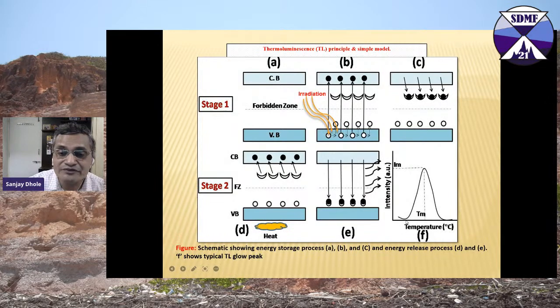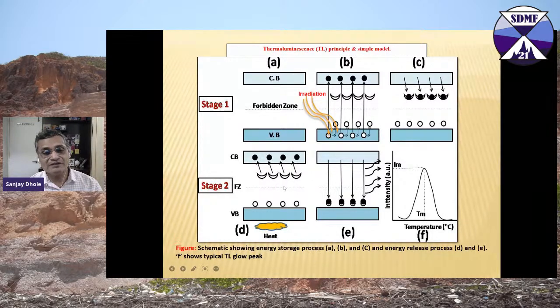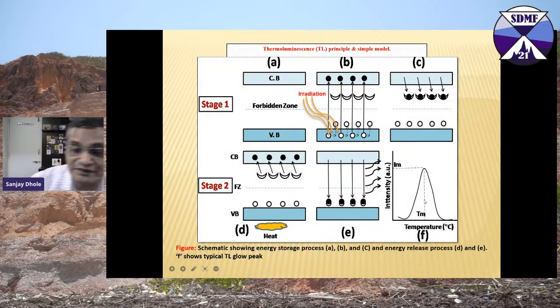When you have a lower temperature, the very shallow traps release first and the light increases, until you reach the maximum temperature where you have the maximum intensity of the photons coming out. As you go on increasing the temperature further, the very deep levels, where the impurities are very small in number, come down. So this is a perfect Gaussian, and this is what is called the dosimetric peak. The area under the curve of this dosimetric peak is nothing but the dose received by that particular sample, and this is how the dose measurement can be done.